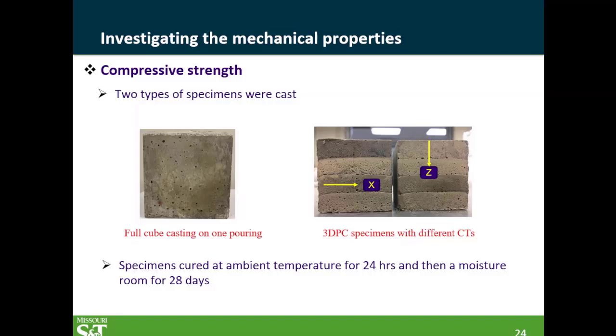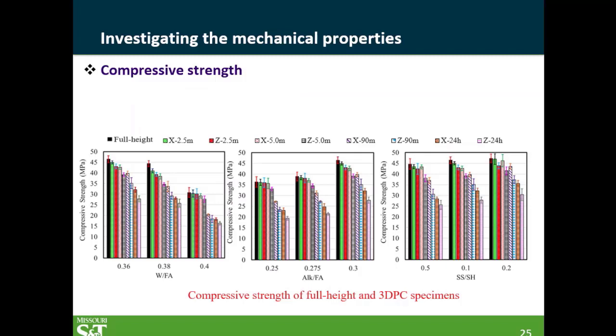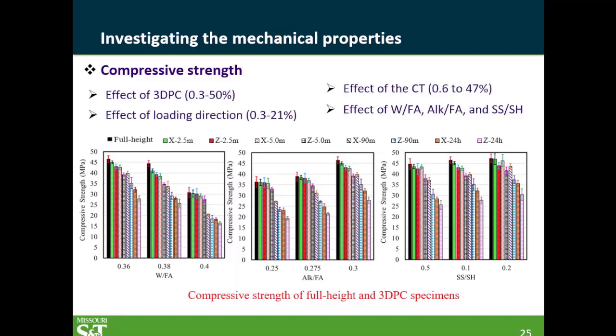So we only use ambient temperature for 24 hours and then moisture room for 28 days. Muhammad is telling me I have only 2 minutes, so I need to move quickly here. So what we found, let me just jump here, with the different loading direction, you can lose up to 20% in terms of compressive strength, and also in terms of different cycle time, you can lose up to 50% of it. If you have a very long cycle time between these layers, you can lose 50% of your compressive strength.